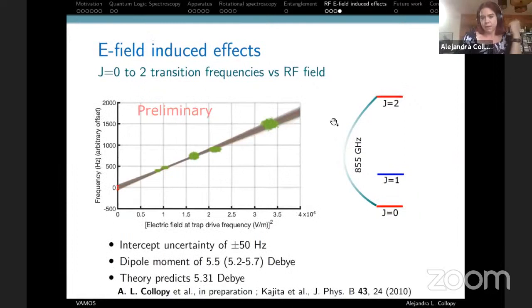If we do some parametric bootstrapping, we can get some good information about our intercept uncertainty and our uncertainty in the slope. We find that the intercept uncertainty we can get down to plus or minus 50 hertz or so for this transition. This is the field-free value of the transition frequency. That's what we really want to know when we're doing spectroscopy. We want it to be a number that can be compared to molecules out in space or something in your trap. The slope with some scaling gives us the dipole moment of the molecule, and we get a 95% confidence interval that looks like this. This is in agreement with theory, which is great.